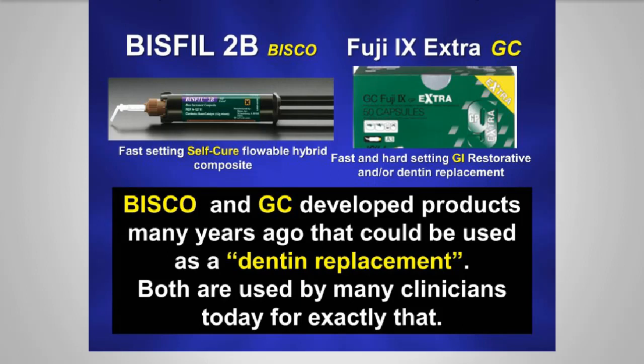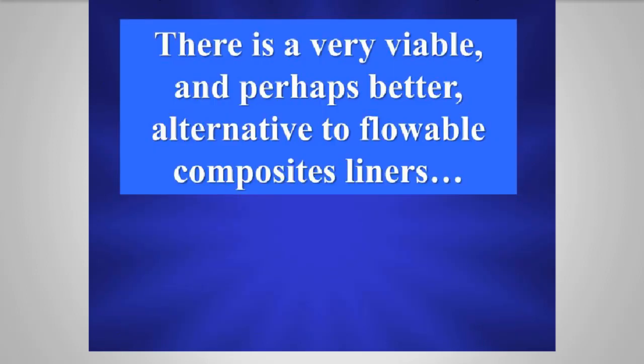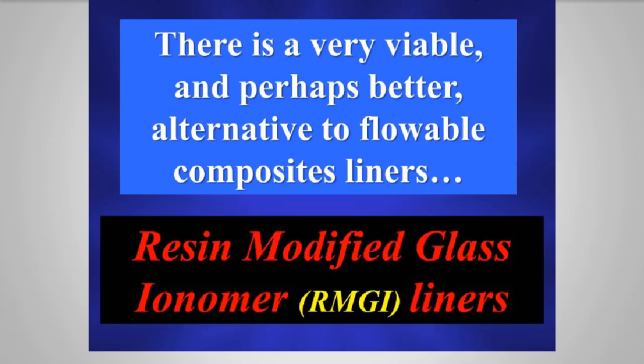Now there's a very viable and maybe even a better alternative in my mind to flowable composite liners, and that's the use of resin-modified glass ionomer liners, which I've been using for many years. And I switched from flowables to resin-modified glass ionomers because I think they're much better at controlling micro-leakage. And I believe most of our composite failures are in fact due to micro-leakage. They're not really falling out. I don't see many bulk fractures. They leak, and they get recurrent decay.